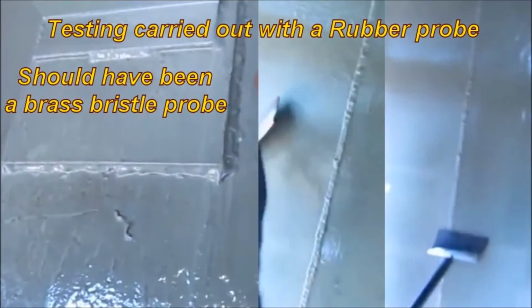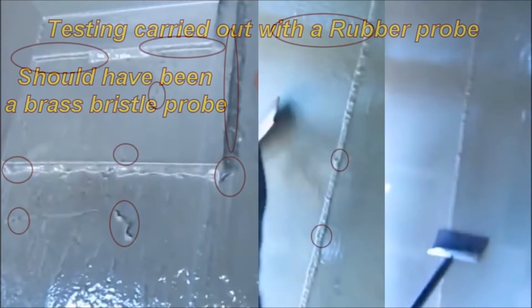This area here has been tested with a rubber probe. The rubber probe on this sort of thing is not suitable. It skips over areas, it's lifted up. If there's any undercut with pinholes along the welds, it will not find it. These are the areas it would most likely miss, as it just could not be tested with a rubber probe. The two oval circles at the top left-hand side of the photo, nothing's going to salvage those because that's stitch welded and it's not suitable for tank work. It's not suitable for any external work.